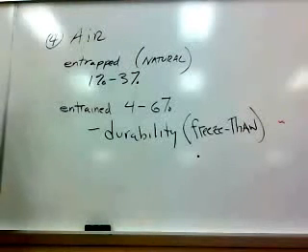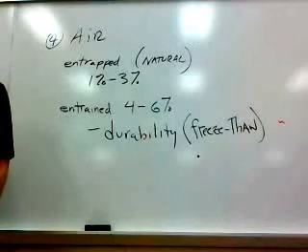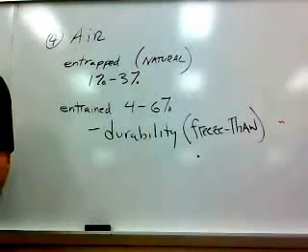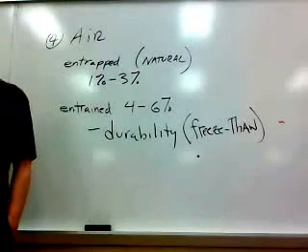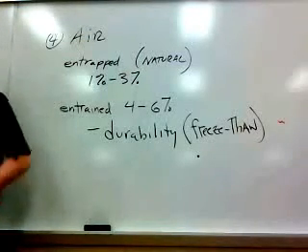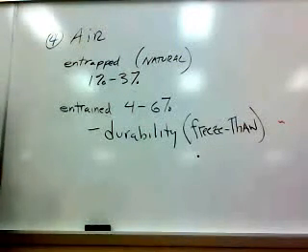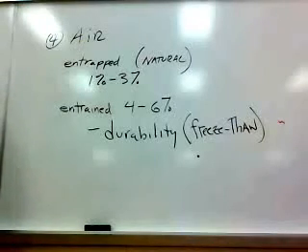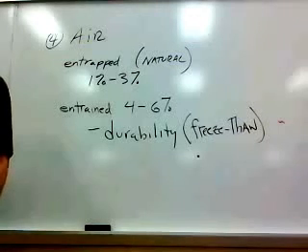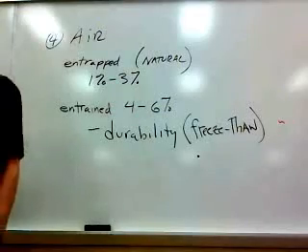Again, there's a trade-off there, though. Although we said lighter, what's a negative of more air? It makes it weaker. Air doesn't really support weight. You've got more air in the concrete, you've got less paste. You know what I mean? It makes it weaker. So there is a trade-off there. That's why we limit it to maybe around 8% maximum air, because we lose a little bit of strength, but we're able to live with it. Anything more than that, it really starts going downhill pretty quickly.